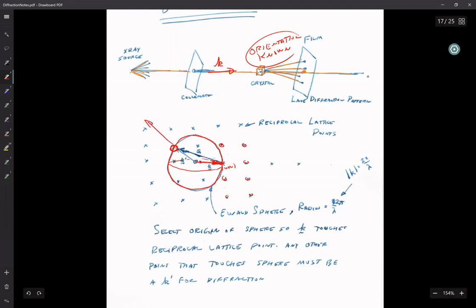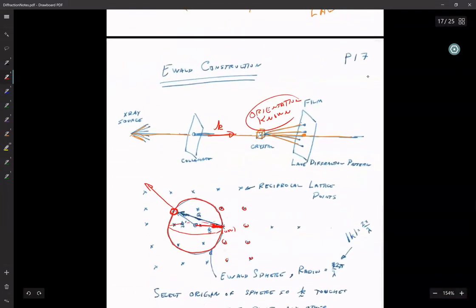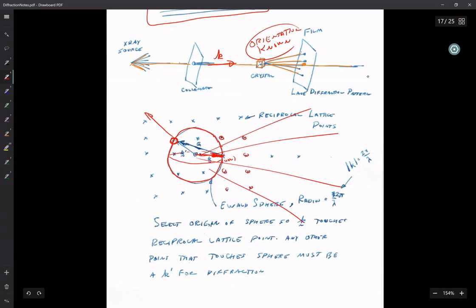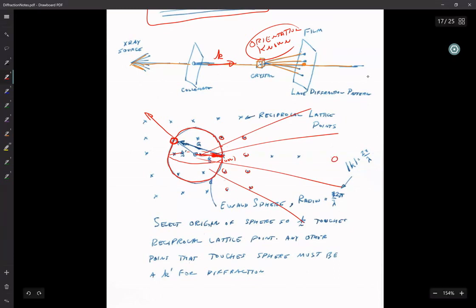This is called the Ewald construction — the mathematical way to think about what's happening. The reciprocal lattice spacing is much smaller than the radius of the sphere in practice, so you wind up with many spots where the sphere cuts the reciprocal lattice, giving diffraction. Because you have a regular grid and a regular sphere, you naturally get symmetry. That's why Laue diffraction patterns always reflect the symmetry of the crystal.